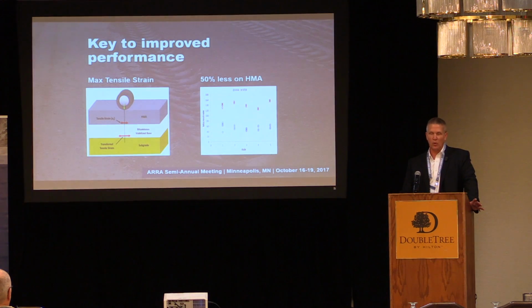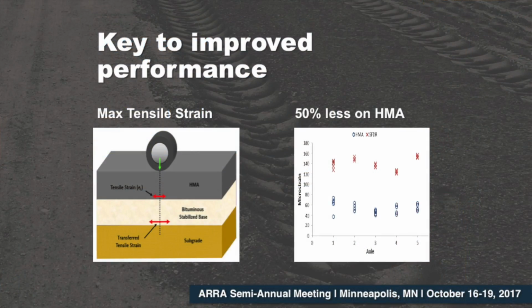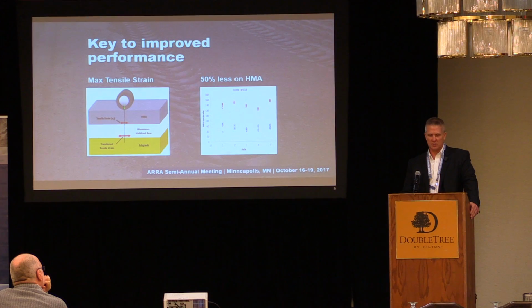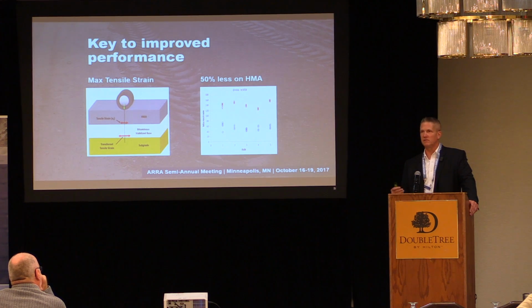And the reason that's very important, you'll be going out to the Monroe facility today. I encourage you, hopefully you'll be able to go on the Monroe mainline test section cells 2, 3, and 4, and those are recycled in place using the SFDR process, stabilized full depth reclamation. But the whole concept here is tying to performance. And when you go out there, you'll see on those sections where on I-94 Interstate Highway, they only had 3 inches, a little less than 3 inches, in fact, of hot mix overlay on top of the stabilized sections.